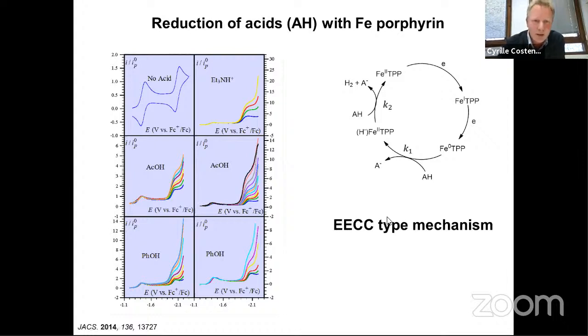And what is interesting here is that, for example, if you look at what's going on using acetic acid as a substrate, okay, you can see that not only by increasing the concentration of acid, you get more and more current, but now you can see that there is also a shift of the wave. So it's not the same situation as the one we've seen previously with CO2, where the catalytic wave, the half wave potential was always at the standard potential.